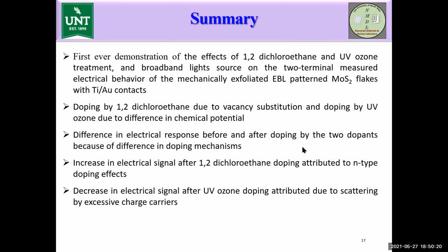And there is an increase in the electrical signal after 1,2-dichloroethane doping attributed to N-type doping effects. And the decrease in electrical signal after UV ozone doping is attributed to the scattering by excessive charge carrier concentration.